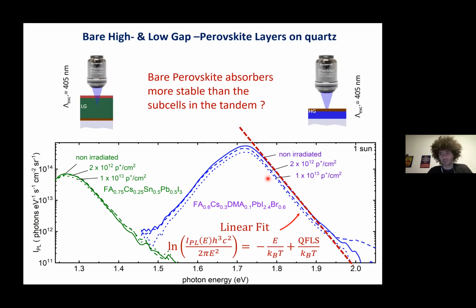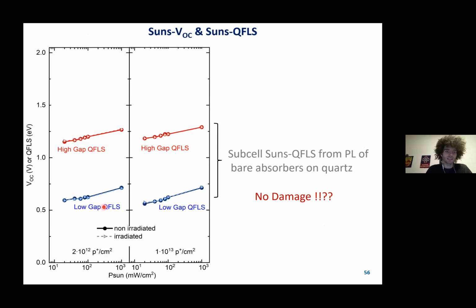So again, as before, I'm now doing a linear fit to the high energy slope of my PL to extract the quasi-Fermi level splitting. And you can do that for a variety of different light intensities, excitation intensities. Then you can plot the quasi-Fermi level splitting of the low gap and the high gap here, before and after two different fluences for proton irradiation.